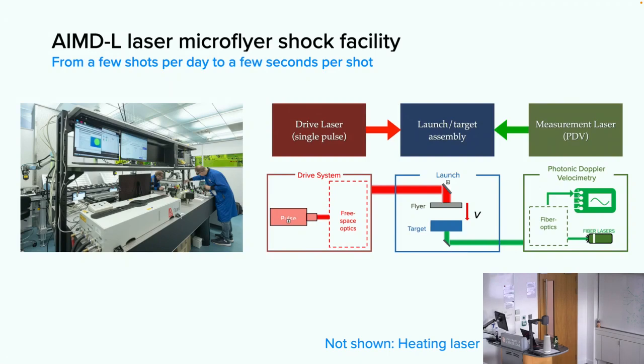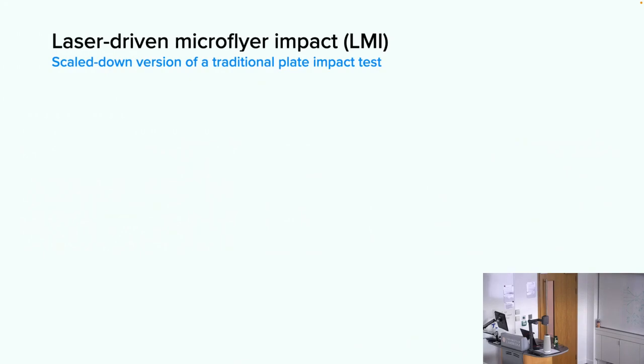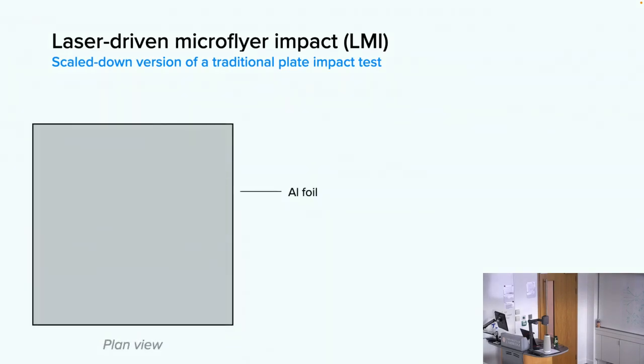The other thing I'll say about this, and I'm not going to talk about this more, is that we have a heating laser now, so we can do measurements not just at room temperature, but at temperatures up to 900 degrees Celsius, which actually these days is only limited by our pyrometer and not by our heating laser. Okay, so let me show you how this experiment works.